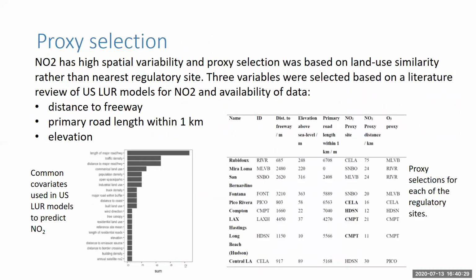The first step in the MOMA process is to define the proxy stations for each of the co-located AQIs. NO2 has a high spatial variability, and so proxy selection was based on land use similarity rather than the nearest regulatory site. 3 variables were selected based on a literature review of US land use regression models and also the availability of data. We chose distance to freeway, primary road length within 1 kilometre and elevation. And in the table to the right are the proxy selections for each of the regulatory sites. And you can see that in some cases the proxy is some distance away from the regulatory site.